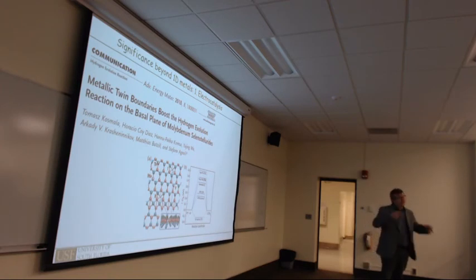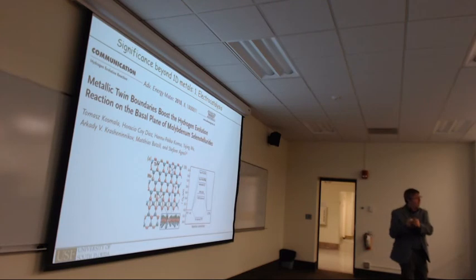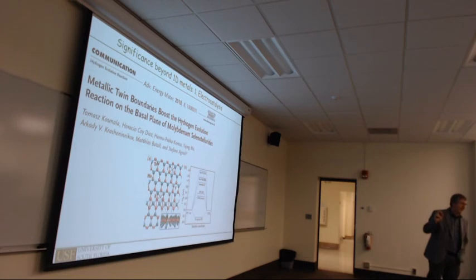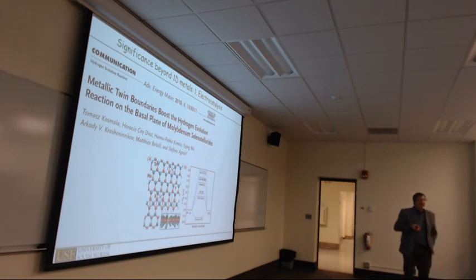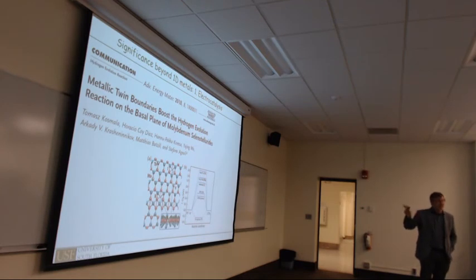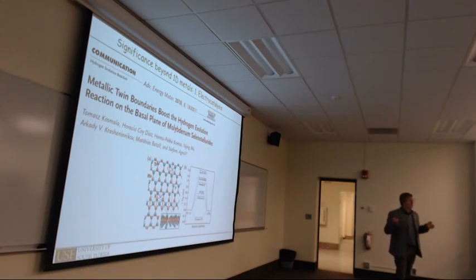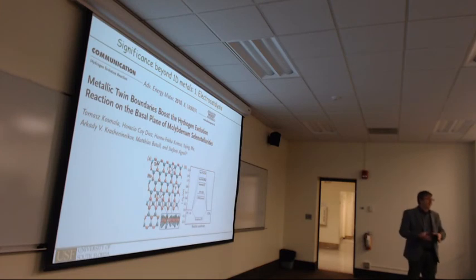So the problem is, if you have a single crystal, molytelluride is probably less stable, and molytelluride you can buy commercially, and you get different flake sizes. Sometimes you get 5 by 5 millimeters, that's larger, and sometimes you get little flakes. Molyselenide is a little larger, but what we've done is for the MBE grown one on a molysulfide substrate, or you can grow it on graphite. You can have a large graphite sample, 5 by 5 millimeter, and grow molyselenide on that and test grain boundaries.